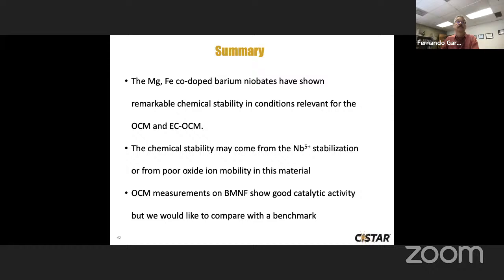So to summarize, we believe that these barium niobate parent structure materials are very interesting in that they're showing remarkable chemical stability, despite the fact that barium is highly reactive to CO2. Barium oxide containing materials are reactive to CO2. We're trying to understand why this is the case. The chemical stability of the structure may be due to the niobium five-plus stabilization or from poor oxide ion mobility within the material. The OCM measurements on these catalysts show good catalytic activity, but we need to compare these to